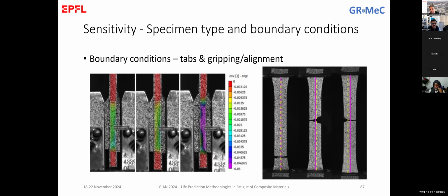In our case here, the material is quite brittle. I wouldn't say it's stiff. The stiffness of this adhesive is around 5-6 gigapascal, but the behavior is very, very brittle. So that's why we've seen a lot of tab failures, and this is why we started investigating the reason for these tab failures. There is a publication, I can share with you later on. It was in the slides.